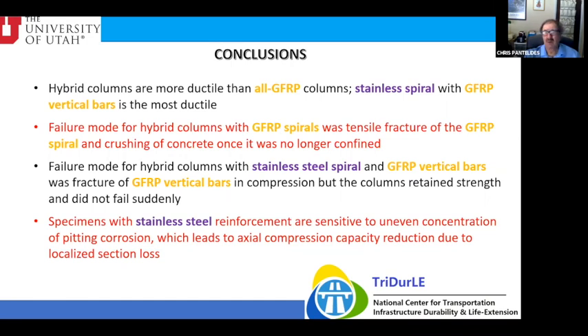The failure mode of the hybrid columns with the stainless spiral and the fiberglass vertical bars was fracture of the fiberglass vertical bars in compression, but the columns actually still retained strength and did not fail suddenly. So the stainless steel spiral gives the more ductile response. However, even the stainless steel reinforcement, we saw, is sensitive to uneven concentration of pitting corrosion, which can lead to axial compression capacity reduction due to the localized section loss. That was something that surprised us.